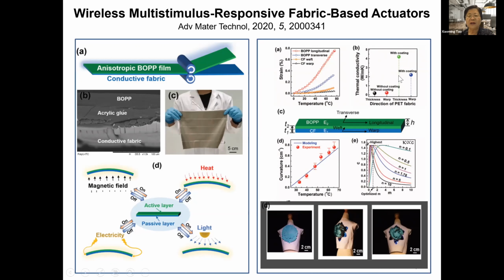Now, in the pictures on the right side, the upper one, you can see that when temperature increases, these components, the film and the fabric, have a large induced thermal strain. Okay, and the difference is very large. Therefore, it's a bimorph structure and causes this buckling or bending deformation of the very thin fabric. And the curvature change, you can see this diagram here is a curvature plot against the temperature, and it almost has a linear relationship. The blue line is a prediction, and the red dots are experiment data.